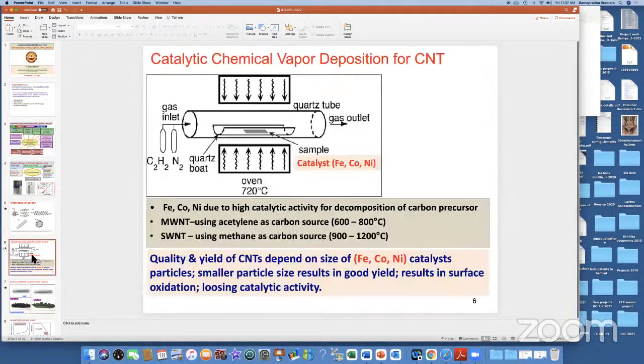So I'll first show how we have taken up the graphene synthesis from a smaller scale to industrial scale. It's a very simple technique. We call it the CVD technique, catalytic chemical vapor deposition. So you can easily understand that you have the quartz tube and a quartz boat where we keep the catalyst, and we allow the hydrocarbon, which is acetylene, ethylene, or anything, at a particular temperature which you have to optimize, and then with the flow rate, one can dissociate the hydrocarbon into carbon and hydrogen.